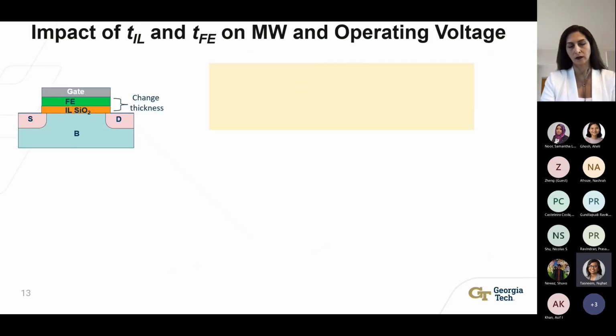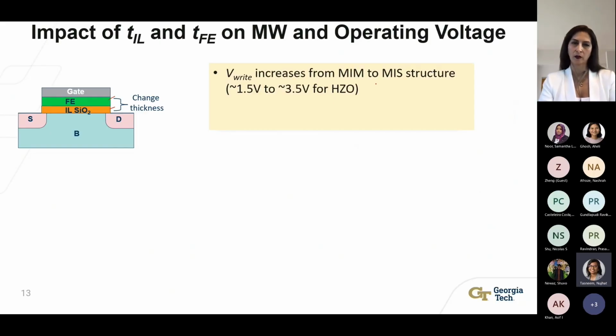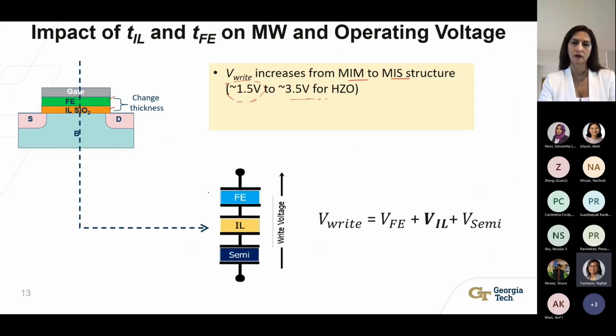One of the first experiments we did on these FeFETs was trying to observe the effect of the ferroelectric layer and interfacial layer on the device performance. For a conventional ferroelectric material, for example hafnium zirconium oxide, the switching voltage is only 1.5 volt. But whenever we move from an MIM to an MFIS structure, the write voltage significantly increases. The reason is that in an FeFET structure, the write voltage depends on the voltage drop across all the layers of the FeFET's gate stack, which is the ferroelectric layer, the interfacial layer, as well as the semiconductor channel. So in this experiment, we changed the thickness of the interfacial layer and the ferroelectric layer and tried to observe their effect on the device operation.